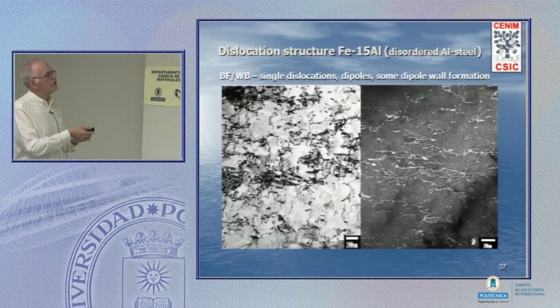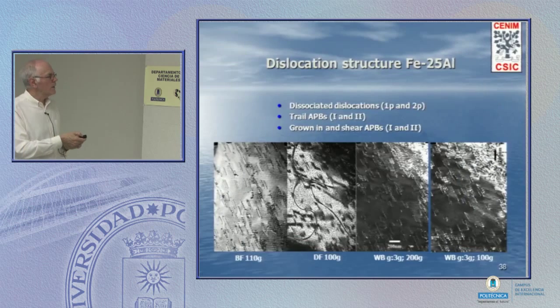When I move to Fe3Al, now what we've got are pairs of dislocations. I hope you can see the pairs here. The front one destroys order, so we pair a second one to repair the order. Here we're looking at the dislocations, and here in different contrast we're looking at the stacking fault, the antiphase boundary.